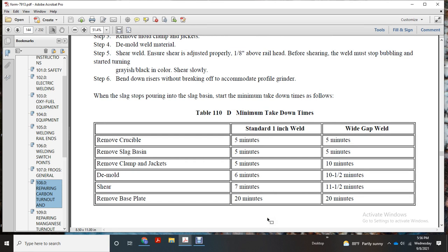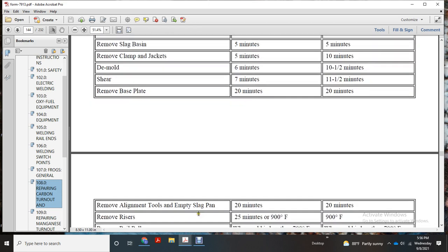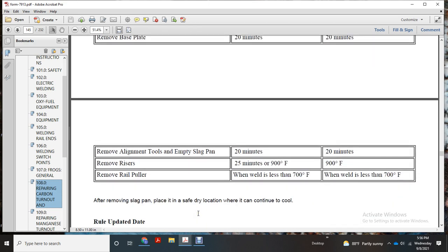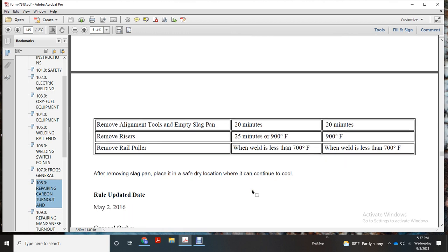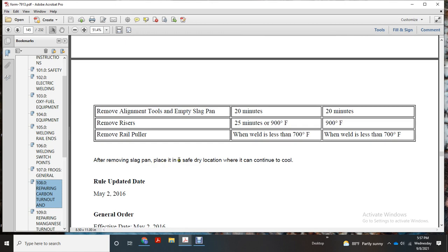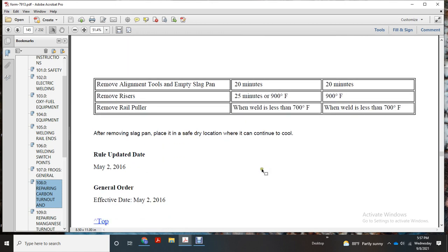Remove the base plate in 20 minutes for standard and wide gap. Remove alignment tools in 20 minutes. Remove risers in 25 minutes, or at 900 degrees Fahrenheit. Wide gauge rail puller, welded wide gap gap: remove the rail puller when the weld is less than 700 degrees, and that goes for both of them. Remove the slag pan and place it in a safe, dry location where it can continue to cool.